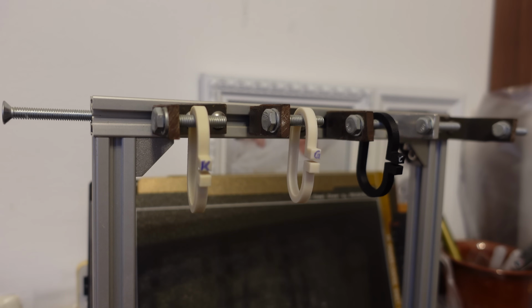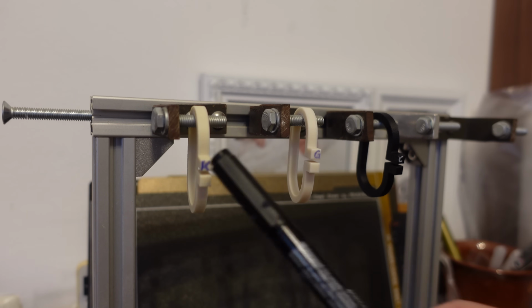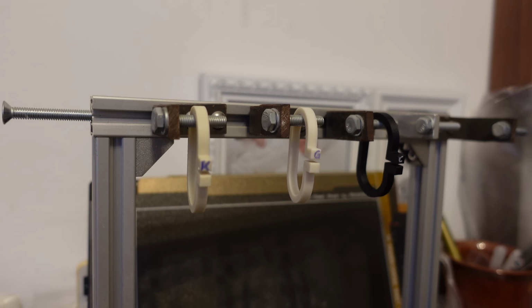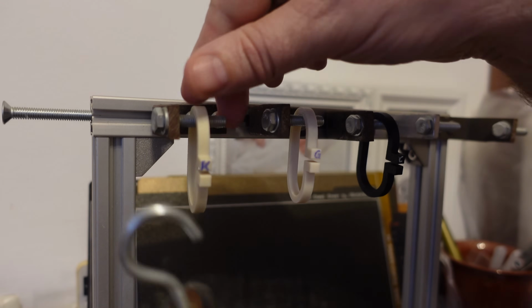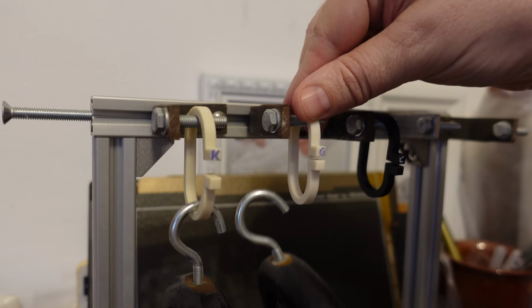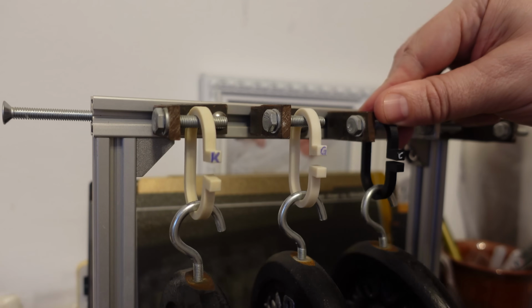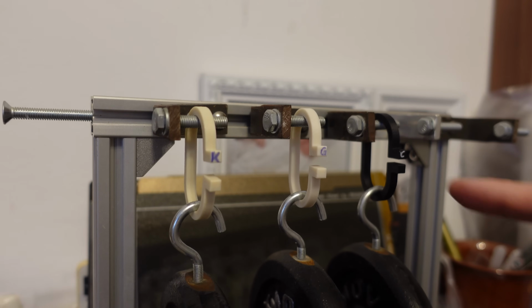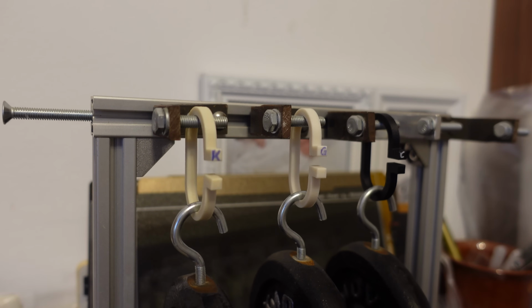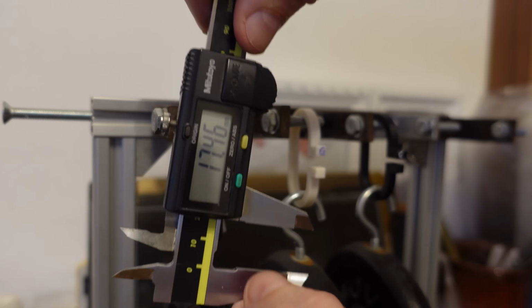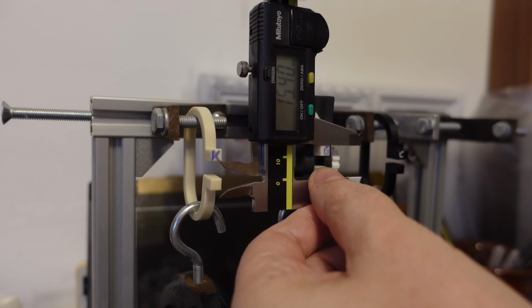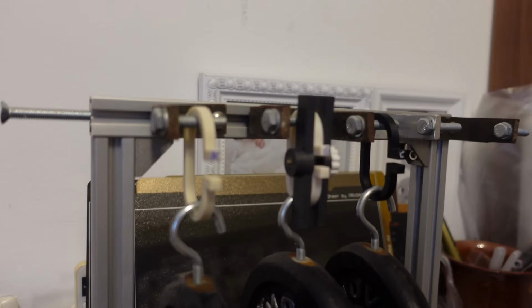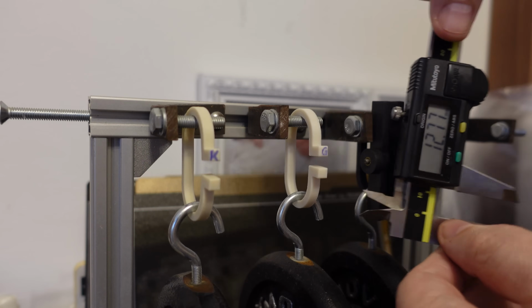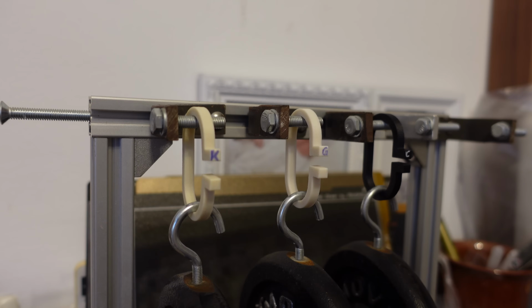Creep, a deformation under constant load: such as Kevlar, glass fibers, carbon fibers. The load is 1.25 kilograms. Visually the smallest deformation is on carbon fiber, 17.46, 15.40, 12.77. So this is their initial deformation, and now let's see the last measuring.